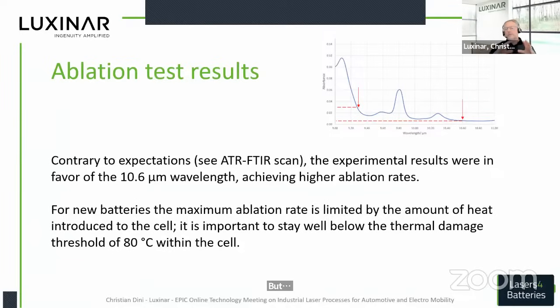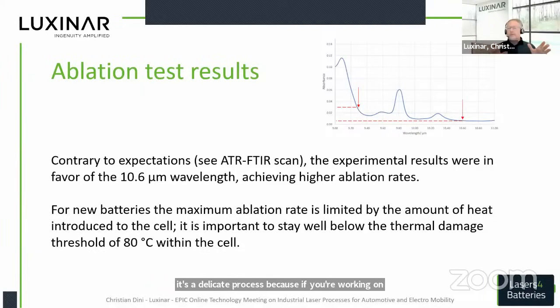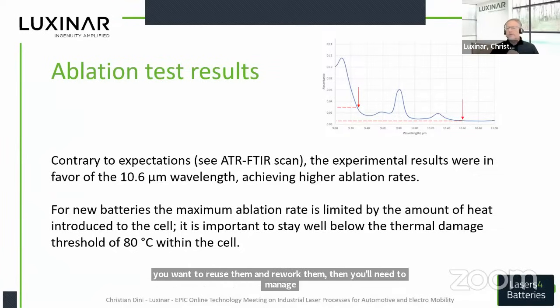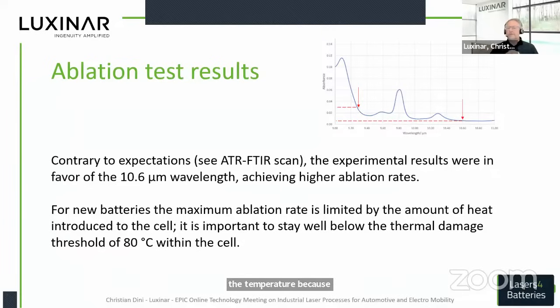But the key technology here is that it's a delicate process, because if you're working on ready-built batteries and you need to unwrap them and you want to reuse and rework them, then you need to manage the temperature, because if you heat up the battery more than 80 degrees, the battery is damaged. So the goal is to have the same productivity as a machine that the workers have, but with less environmentally unfriendly materials, more protective to the battery itself, and not damaging the inside of the battery. And that all was achieved.